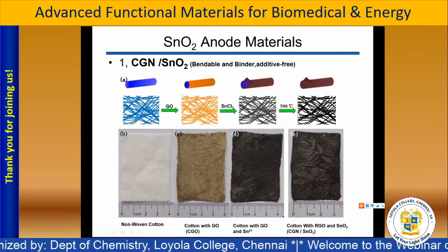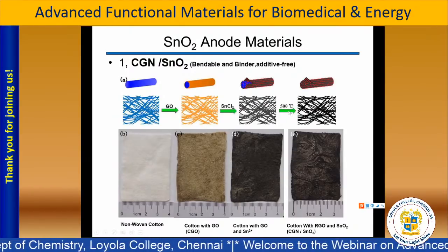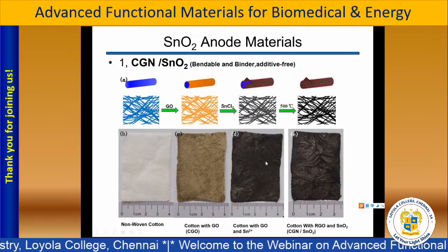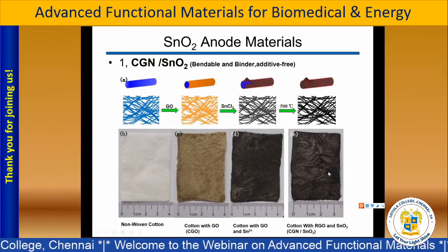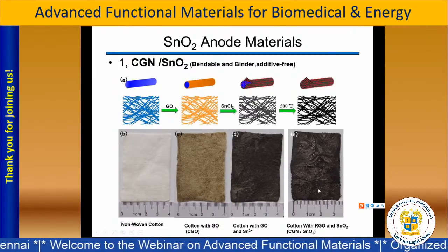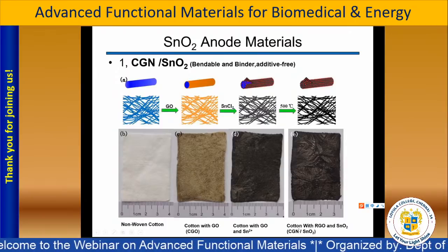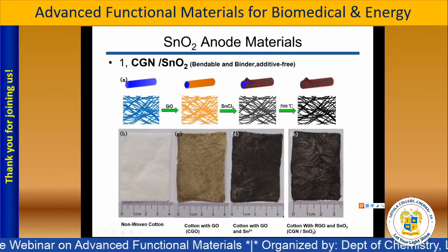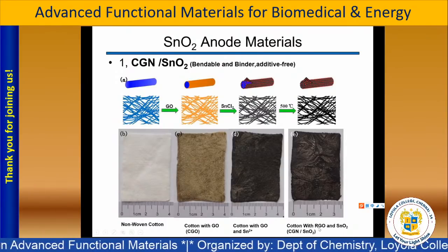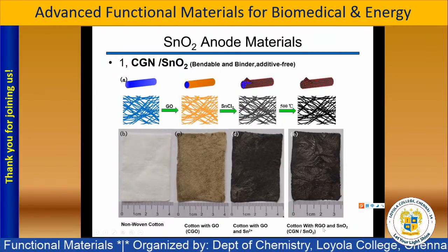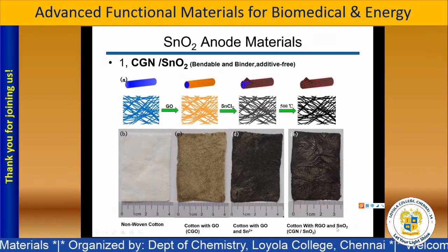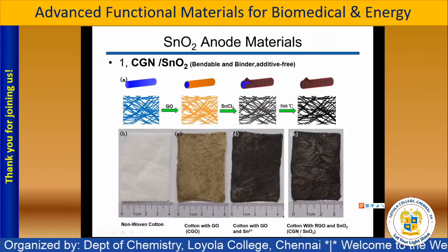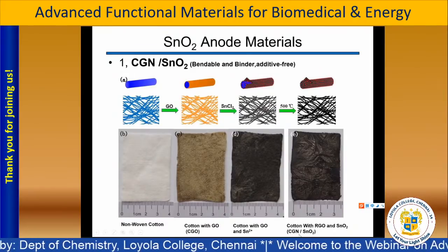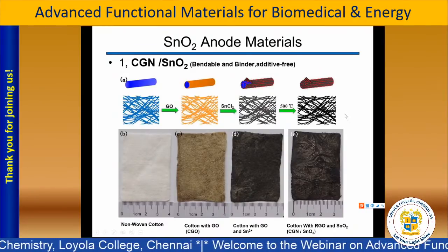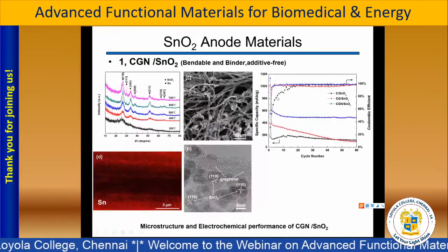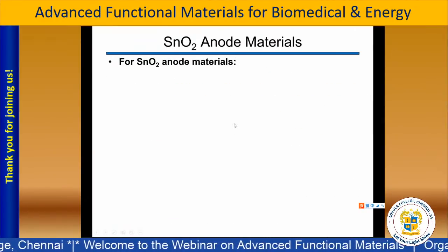and then heat treatment is applied to this material, and we got the anode material, which is a cotton with RGO. RGO is a graphene. We can think of it as graphene and tin oxide. So we named it CGN tin oxide. Let me show the microstructure of this material.